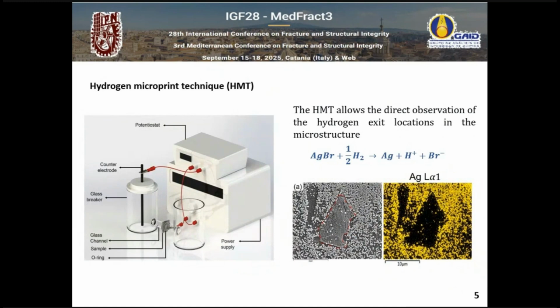Well, my colleagues in Canada also used this technique called hydrogen microprinting, which allows us to see where the hydrogen is passing through in the microstructure. The principle is similar to photography. They put a layer of silver bromide. So the silver bromide reacts with the hydrogen. The silver precipitates in the form of tiny droplets, and the hydrogen and the bromide just go into the solution. Then by scanning electron microscopy with EDS, we are able to identify these tiny silver drops, so we can see where the hydrogen is coming out of the plate.